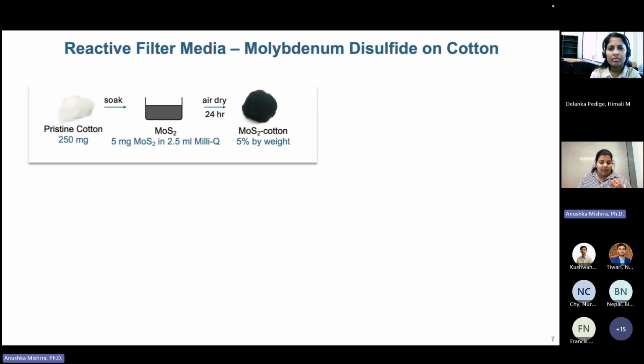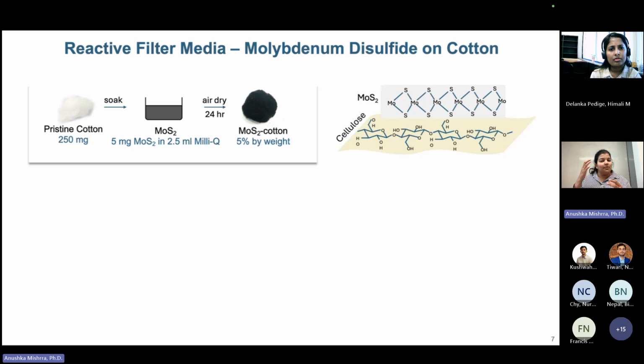The cotton wool's properties, like it can absorb a lot of water, actually helps, because when we put the cotton wool in a MOS2 water suspension, the MOS2 immediately absorbs onto the wool, and if you dry it, it can really bind well with it. I think it's something to do with the cellulose structure and how the sulfur atoms in the MOS2 bind with them. And definitely there's scope for more research on how that interaction happens.